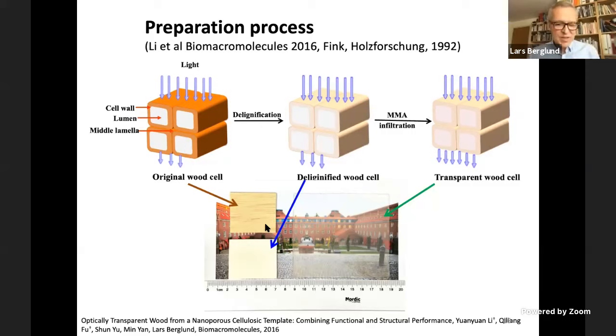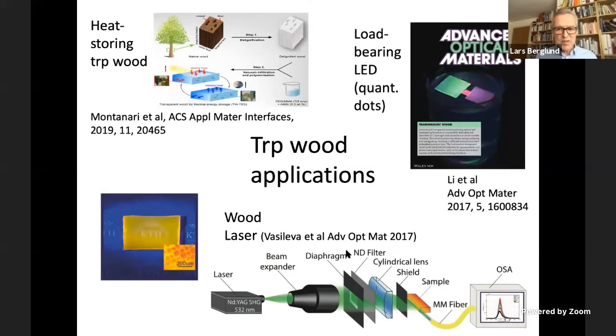This is something which is quite interesting from the, let's say, phenomenological point of view, but the procedure is quite straightforward. You basically remove chromophores from lignin. You can either remove all of the lignin, well, most of the lignin, or you can just bleach it. Then you fill with polymer which has the right refractive index, and then you don't have the same amount of scattering sources, and you can have fairly good optical transmittance. So we've used this for many different applications.